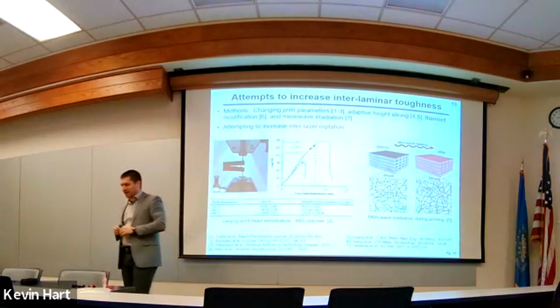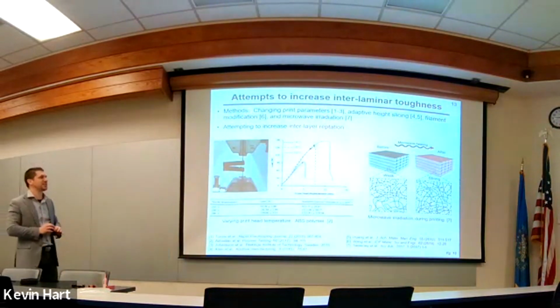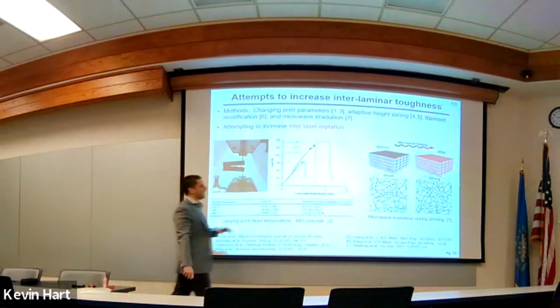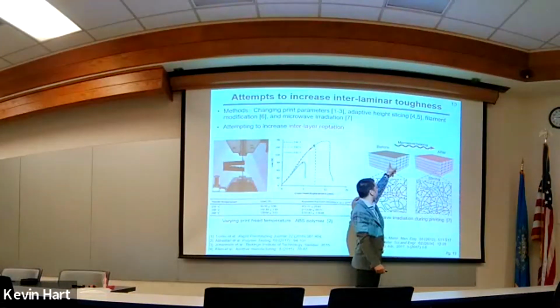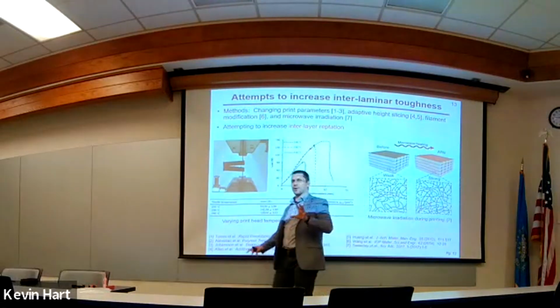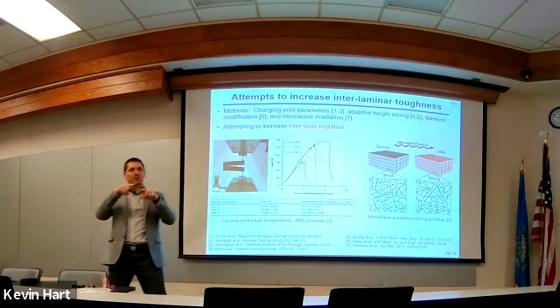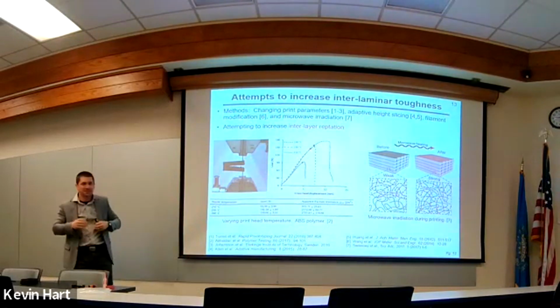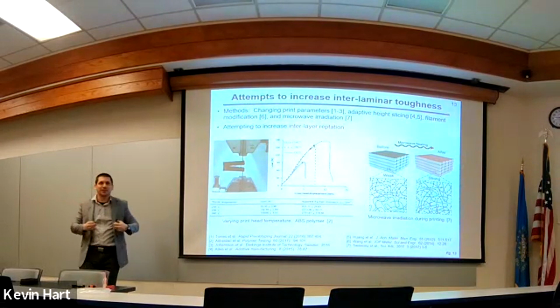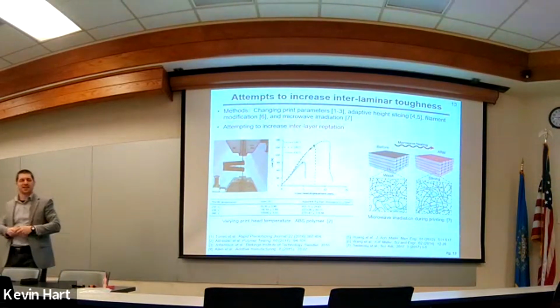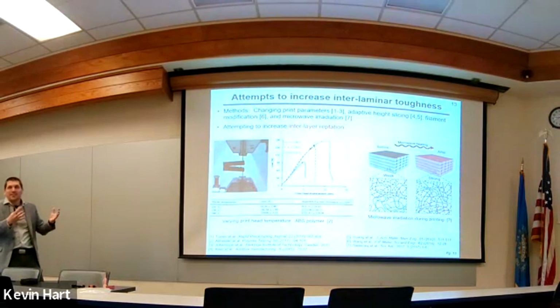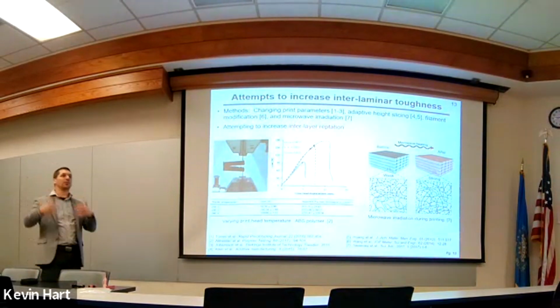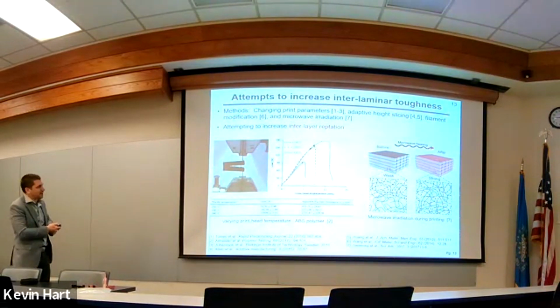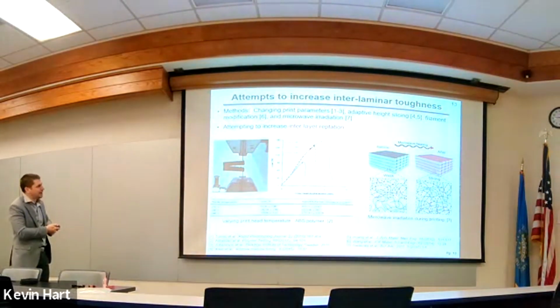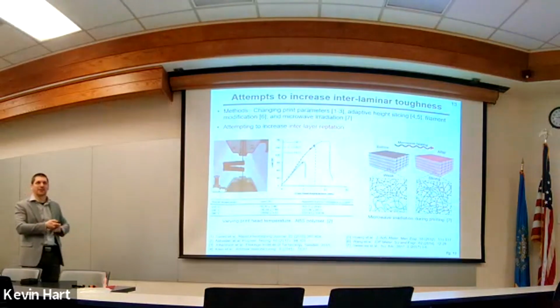There are some other slicker ways that people have tried to do this. Another interesting technique came out of Texas A&M, where people were making filaments that had carbon nanotubes around the very outside of the filament, and then using microwave irradiation to excite the carbon nanotubes at the printed layer between the two interfaces, so that the polymers would migrate across that interface and recover it. Basically, you put your sample in a microwave and locally heat it at the interface so that it would weld between the layers. They visualize that by saying, here's polymer spaghetti of layer number 2, here's polymer spaghetti of layer number 1. Now we put this in a microwave and they all commingle together and heal that interface back together.